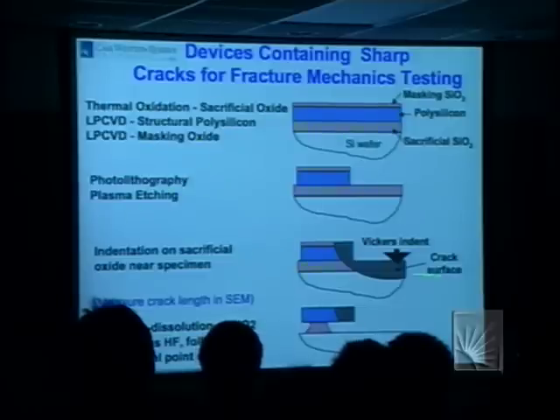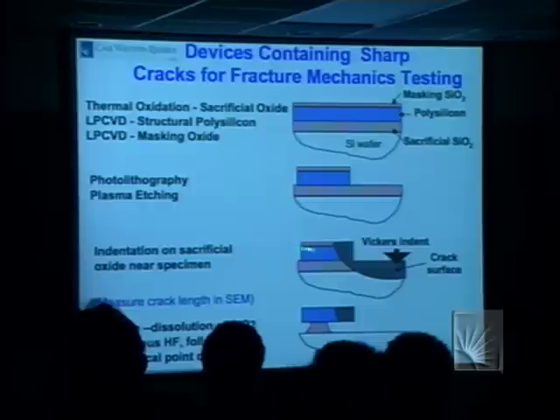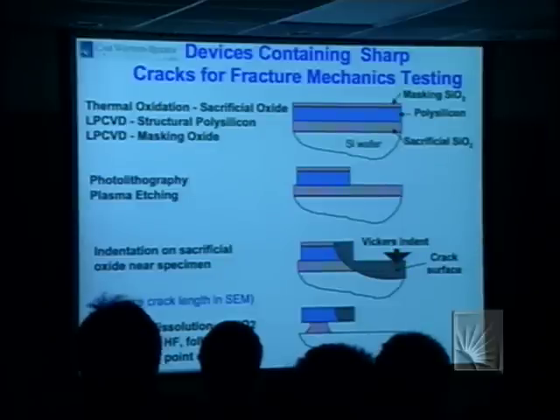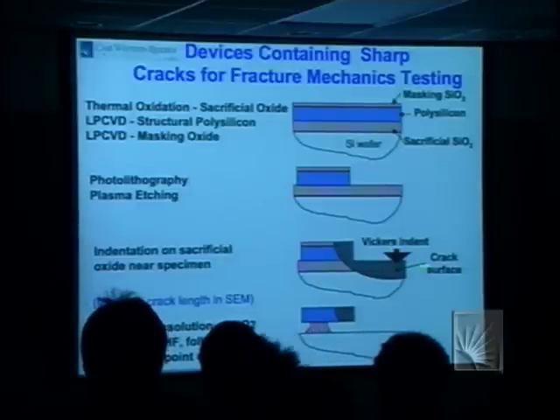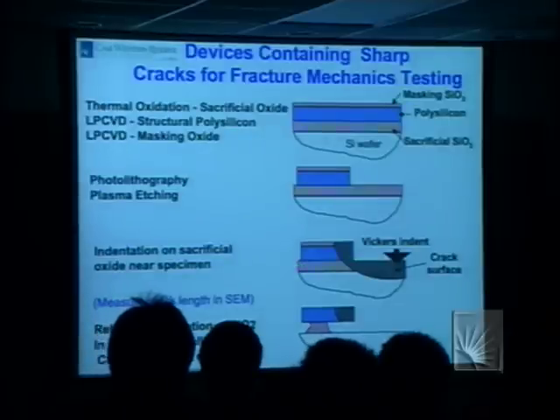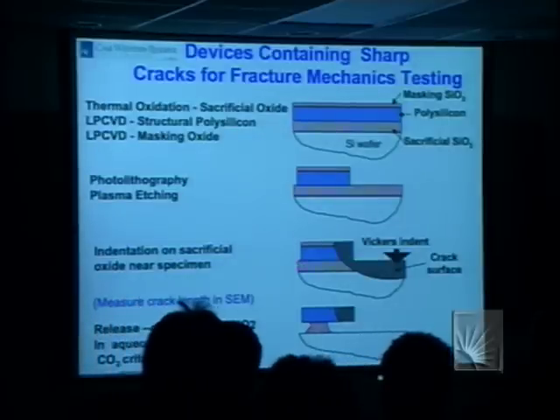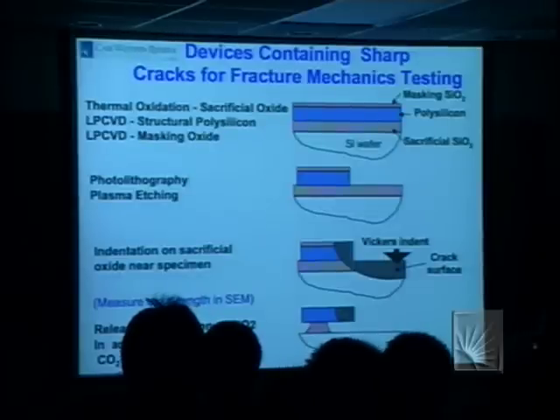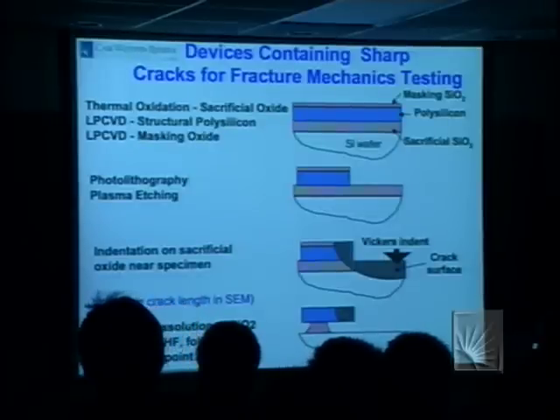But now what we do is, after we get to this stage, we actually put a Vickers indent, not in the device, but in the sacrificial oxide. And it's an overloaded Vickers indent such that there are cracks coming out of the corners. These cracks propagate right up into the device. Then, prior to release, we measure the crack length. And then we release the structure and look to see which devices failed and which didn't. That will be clear in the next slide.